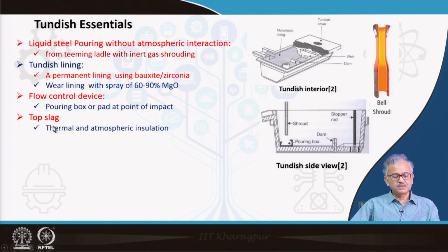And then thermal slag, you have a top slag, basically for thermal and atmospheric insulation. To restrict the atmospheric interaction, you use some kind of top slag or flux on the tundish top, such that oxygen and nitrogen cannot come into the liquid steel. It acts as a barrier, and it also restricts the heat, because you have to use some kind of flux that is insulating also.